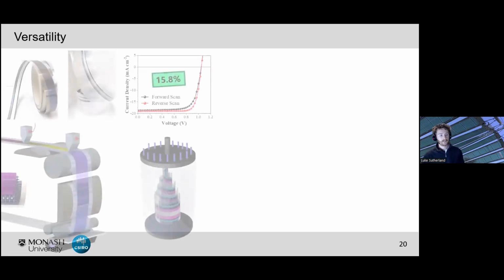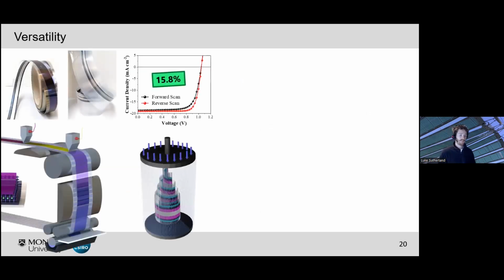And then finally, looking at the versatility of this technique. Not only were we able to fabricate devices on rigid glass-based substrates, we were also able to use the CIP technique to fabricate the roll-to-roll fabricated devices, as I was talking about before. And we're able to achieve efficiencies of up to 15.8% so far, but we believe we can push this even further.